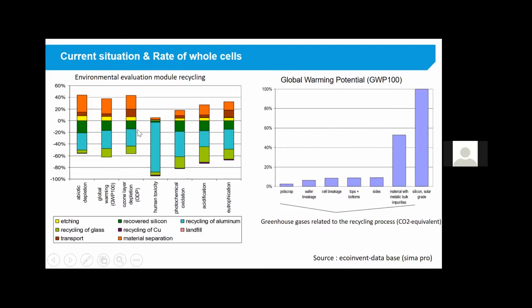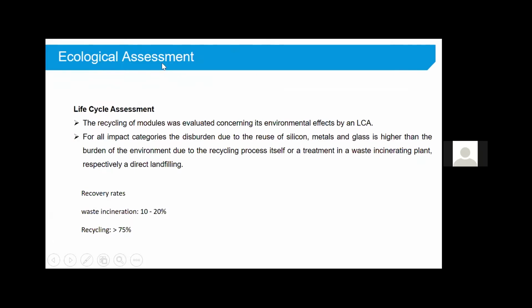If we do the recycling, what happens in future? This is the ecological assessment or life cycle assessment. After the recycling, the recycling of the module was evaluated concerning its environmental effects by a life cycle assessment for all impact categories. The burden due to the reuse of silicon material and glass is higher than the burden on the environment. So if we recycle it, we can reuse it, and they show the recovery rate: silicon recycling 75%, and other waste would be 10 to 20%.